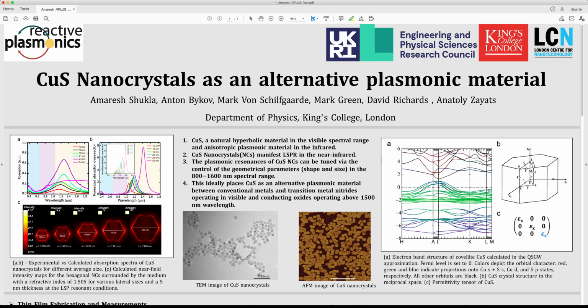widely tunable by changing the size and shape of the nanoparticles, and its range can be between 800 to 1600 nanometers. This range ideally places copper sulfide in a desirable position, filling the gap between conventional metal and metal nitrides operating in the visible and conductive oxides beyond 1500 nanometers.